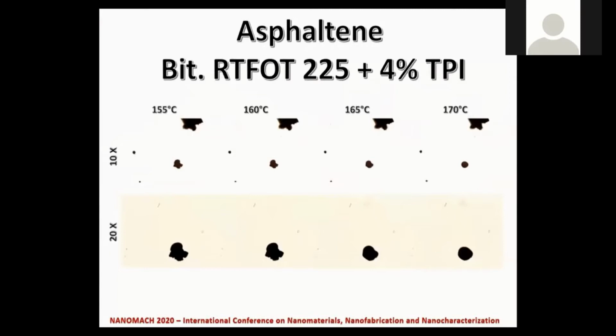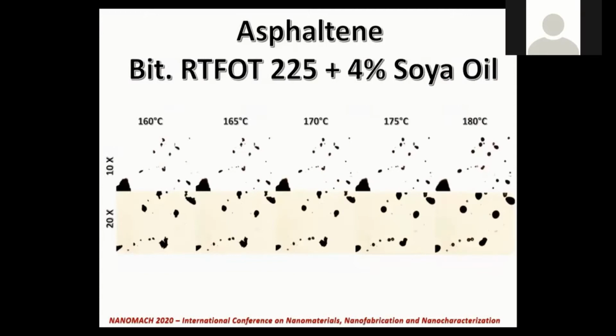The asphaltenes derived from the sample added with 4% TPI begin to melt at 155 degrees and are completely liquid at 170 degrees, showing a behavior very similar to those derived from non-aged bitumen. While the asphaltenes derived from aged bitumen added with 4% soy oil instead show values similar to those recorded for asphaltenes of aged pristine bitumen, 160 degrees, 180 degrees.